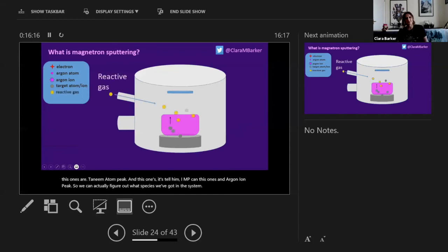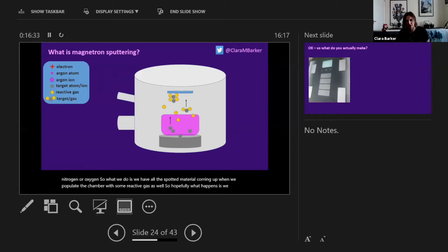What we can also do with all of these techniques is introduce a reactive gas, so nitrogen or oxygen. We have all this sputtered material coming off, and we populate the chamber with some reactive gas as well. Hopefully we form compounds, we form molecules. So instead of having titanium growing on our film, for example, if we introduce oxygen, we can grow titanium oxide. And again, by changing the energy to the system, we can change whether we have rutile or anatase or a mix of that titanium. So we're changing the structure of this material again.